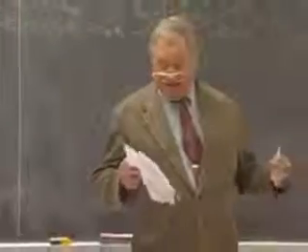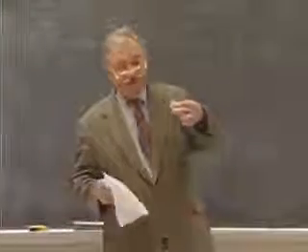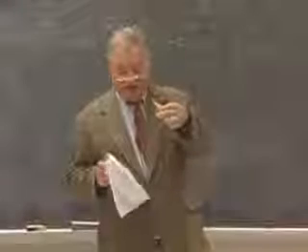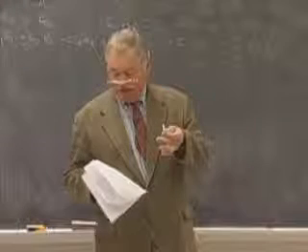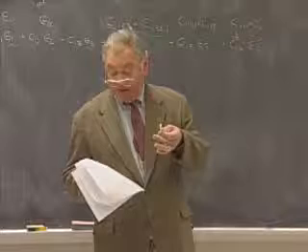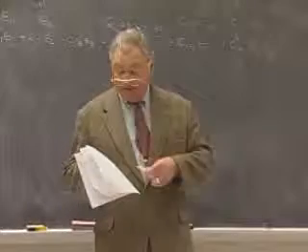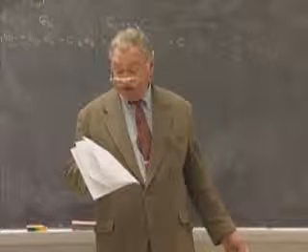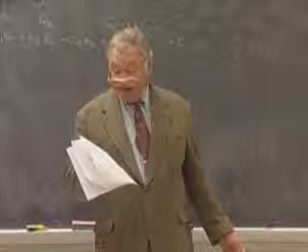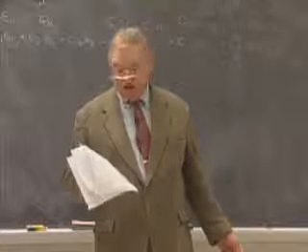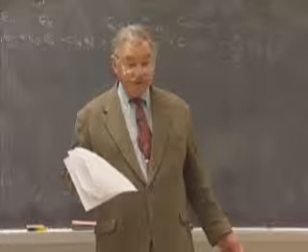And finally, you assume that the crystal is under no state of initial stress. Because if it is under initial stress, you've squished it, you've stretched the bonds, and the forces, not to a major degree to be sure, but the forces will not truly be perfect central forces. So if all three of these assumptions are satisfied, then you have an additional equality, C12 is equal to C44. Okay?